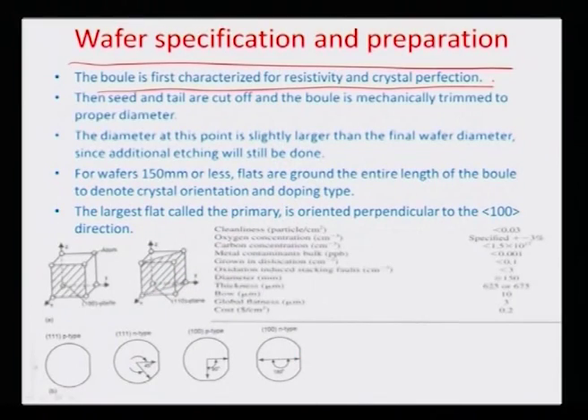Apart from that, there are several other specifications of relative importance. For example, you can have cleanliness in terms of particles per centimeter square on the surface area. You can have indication of oxygen concentration per centimeter cube, that means per unit volume, carbon concentration per unit volume, metal contaminants in terms of parts per billion within the crystal lattice, and then also you can have per unit area, what are the grown-in dislocations. Sometimes these are very well measured using sophisticated non-contact optical characterization tools like interferometry, etc.